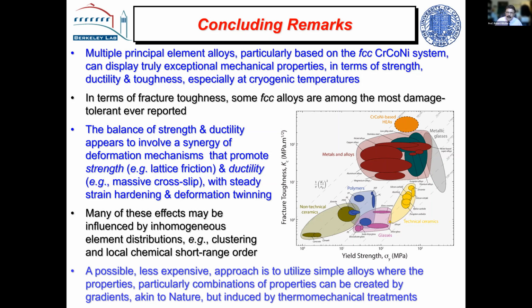Where you have a random solution, the stacking fault energy is low, and when you have one with short range order, it increases the stacking fault energy. So yes, this was actually my question.